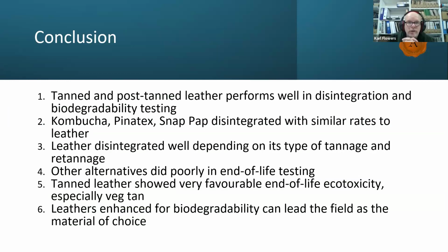They all did quite well in disintegration and biodegradation to varying degrees. As we said, as you start to put more vegetable tan, condensed vegetable tans in, you start to see a decrease in disintegration. The kombucha, the Pinatex, and the Snap Pap disintegrated with similar rates to leather. They are largely cellulosic. You'd expect them as natural materials to break down quite well. They don't break down as fast as leather, though.